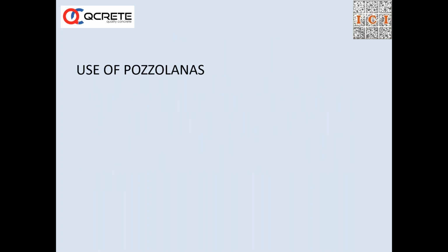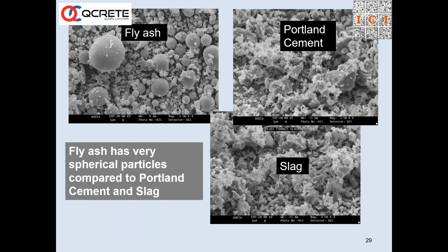And use of pozzolanas, it goes without saying, is to make durable concrete, and this is how these pozzolanic materials contribute. And this is the basic microscopic structure of different materials: fly ash, Portland cement, and slag. What I want to bring to your attention here is that fly ash particles are spherical in nature. When the particles are spherical, it gives better workability, and it is said that if we replace about 25% with a good quality fly ash in a mix, it gives a water reduction of 6% to 8%. So when this water reduction happens, automatically the durability and other properties will increase.